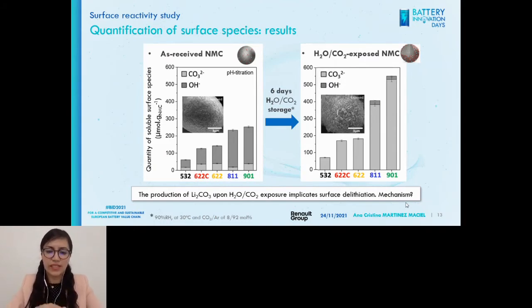We did this in a controlled atmosphere, so it was reproducible, imitating the atmosphere that the films will see in a factory—an exposed dry room where they control the humidity amount. On the left, for the as-received NMC, you can see the amount of carbonates and hydroxides on the surface of these 5 NMC materials.